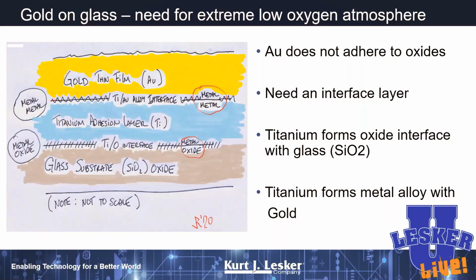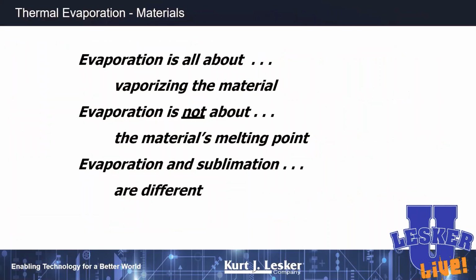And if we do this all without breaking vacuum, you can get your gold to stick to titanium pretty nicely. Now, if you have to break vacuum and expose your titanium to the atmosphere, you're going to have a titanium oxide layer here, and your gold won't stick to that. So just be really, really mindful when you're trying to put metals on things. Certainly gold, gold does not want to stick to oxides, and so you've got to have a nicely sophisticated system to do that.